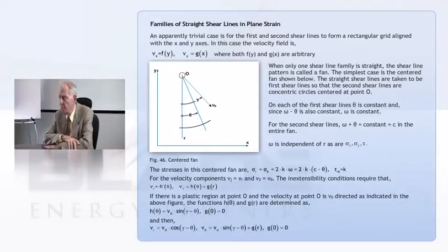And if you went to say, what is the velocity field in here, you get this strange result given in the first pair of equations on that slide. And you get that the x velocity is an arbitrary function of y, and the y velocity is an arbitrary function of x, which sounds pretty general, but it really isn't.